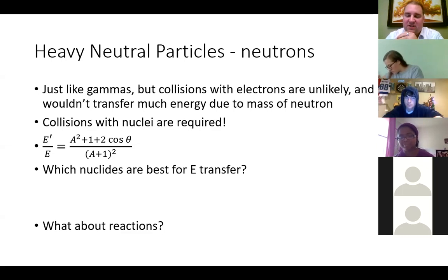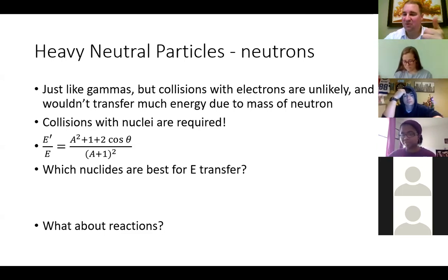So what kinds of materials have a lot of hydrogen in them? Because, of course, hydrogen gas isn't going to be so great. I said hydrocarbons. Hydrocarbons. And what form do hydrocarbons take when they're solids? What do you call those? Polymers. Polymers would be good. Solid lipids are known as fats, or I'm thinking wax. So like paraffin wax used to be used as a shielding material for neutrons, okay? Polymers are great. Plastics would be great for absorbing neutrons as long as they were high hydrogen containing polymers. You wouldn't want a lot of double bonds or stuff like that.